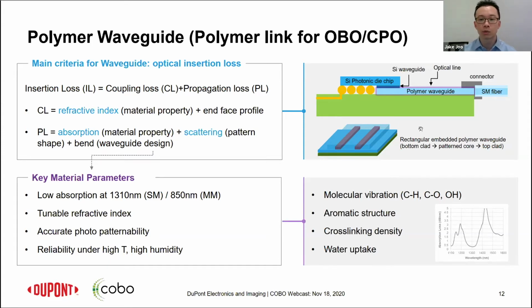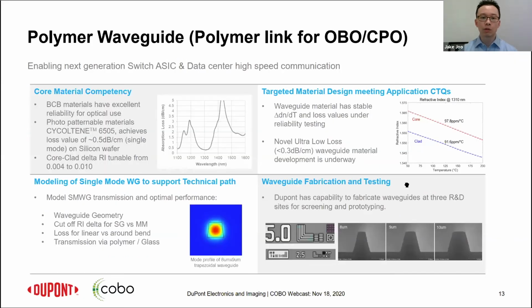And that will turn into some of the fundamentals, right? You need to make sure that this 1310 nanometer absorption, mostly coming from molecular vibration of carbon-hydrogen or OH groups, is controlled. Consider whether we want to put in aromatic structure or not to have more rigid structures, cross-link densities, as well as water uptake, because once you have water, that can increase absorption at the 1310 wavelength as well. DuPont has been working in this field, not necessarily in optics but in general in these types of materials, for quite some time. We worked on a benzocyclobutene-type material, a photopatternable material called Cyclotene, and we use this one as an example of utilization for photonic integration.